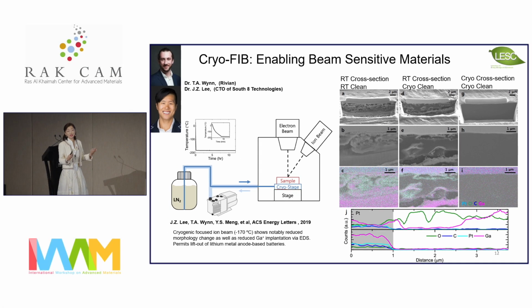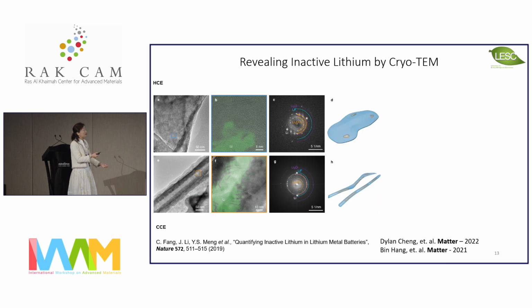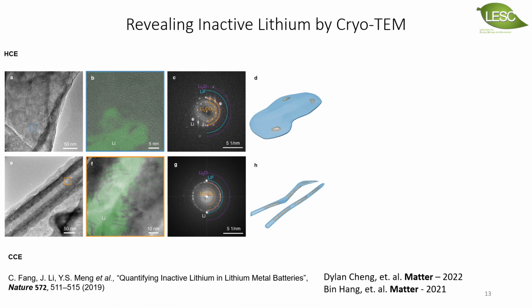However, I was very fortunate at UC San Diego. Many colleagues in the bioengineering department started to use cryogenic imaging techniques. And lithium metal does not go through phase transformation until below minus 186 degrees Celsius. So we can borrow the tools to look at the cross-section of the lithium at low temperature. And these cryogenic techniques let us visualize lithium at the micron scale, and this is cryogenic TEM. You can look at the lithium at nanoscale. This is a 5 nanometer scale bar.